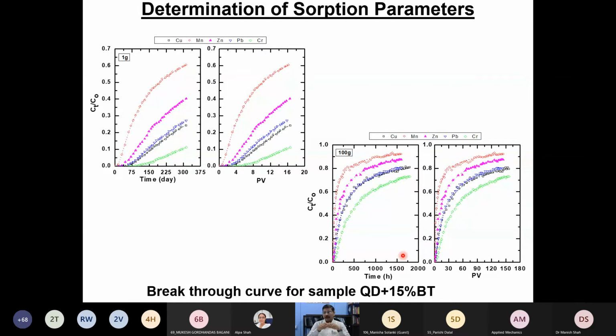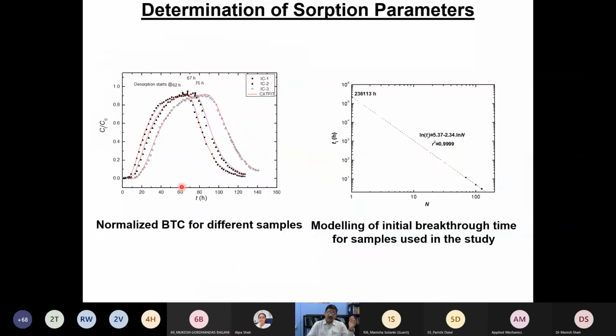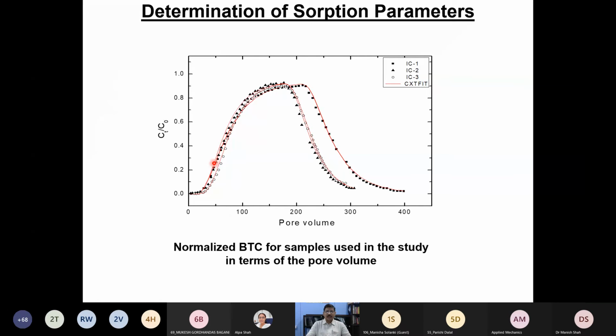the system very well. So we got the breakthrough curves from the centrifuge test as well as the 1G test, because we cannot really wait for many years in a 1G test. So we want to correlate the response of this one. We have also conducted the centrifuge test to see the effect of G, and then we tried to see how this value is going to change. And then if I present it in terms of the pore volume, more or less I have the same kind of response.